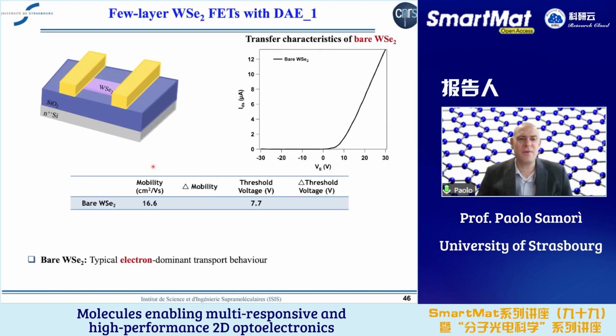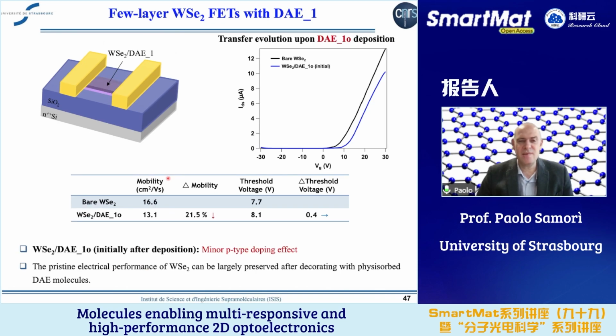And so we start from the pristine tungsten selenide device. It's not an optimized device, so you can see mobility is not extremely high, but it's still not bad. Then we place the diarylethene in the open state, physisorbed on the top. And so we observe a minor p-doping effect with a minor decrease in the n-transport and the electron mobility of about 20%.